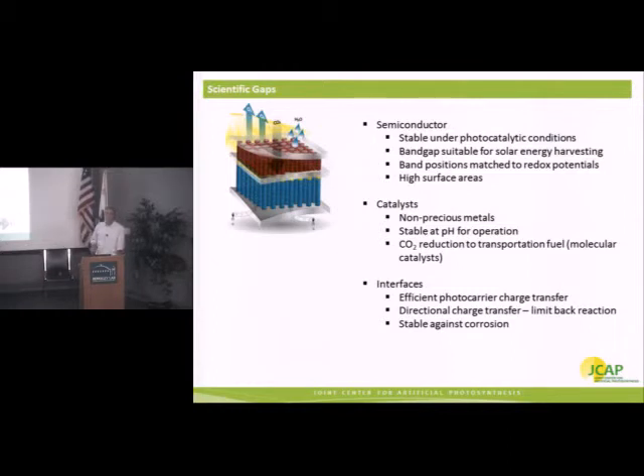So interfaces are essential to the success of a project such as this. You can have a very highly functioning catalyst, a semiconductor that's optimized for solar absorption and with bands in the correct positions, and you bring them together and you create interfacial defect states that lead to charge recombination and complete efficiency losses that dominate the performance of the device. So we need to engineer these interfaces with a high degree of precision.